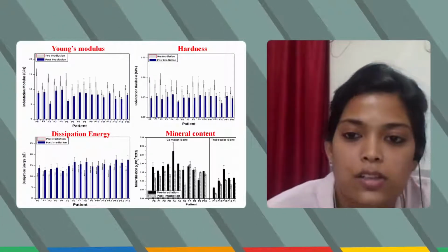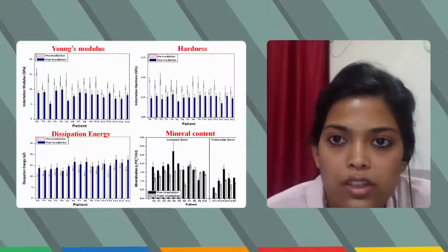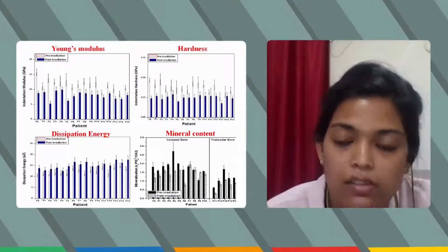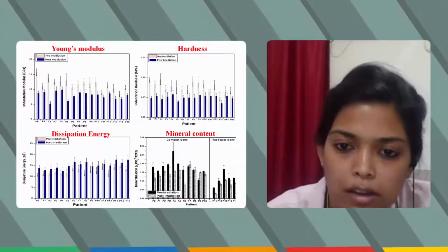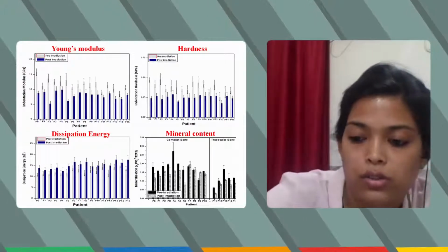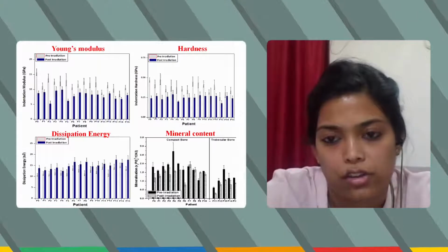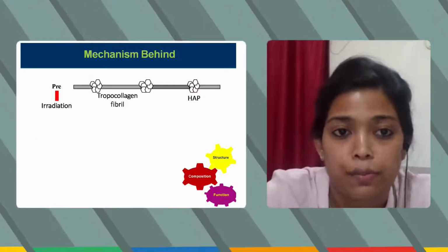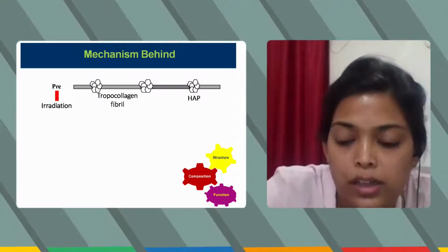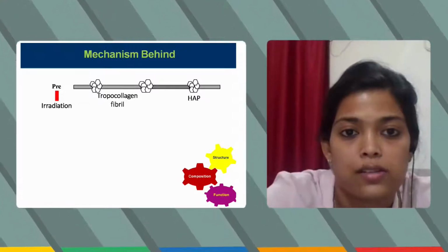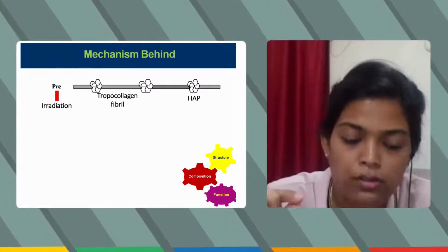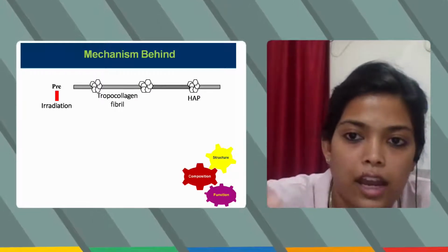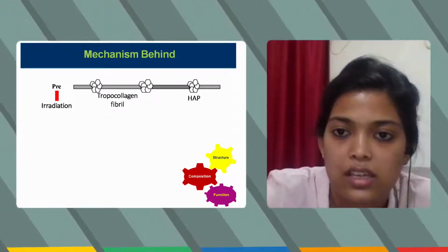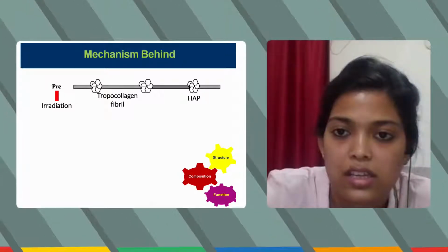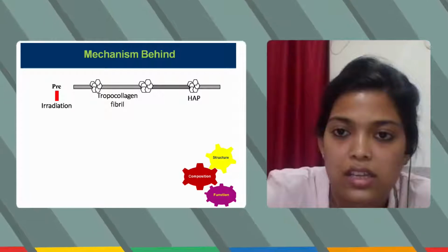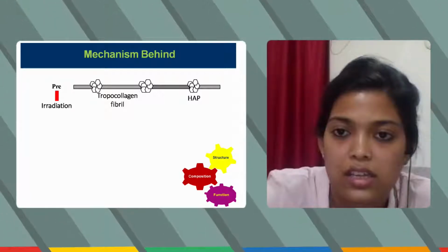So mineral content is a leading factor why everything is changing. The first thing is, when we have less mineral, we have lower Young's modulus, we have lower hardness, but we have a higher dissipation energy because now the response is coming from an organic material, or collagen, I should say. So what is the mechanism behind? The bone at the mineralized level, I have shown you in the previous slides, is from one collagen to another collagen, and in the middle we have hydroxyapatite mineral particles. So this is the condition when we have pre-irradiation bone.